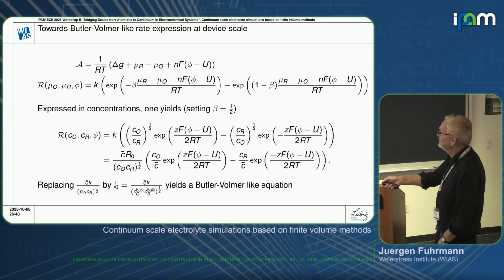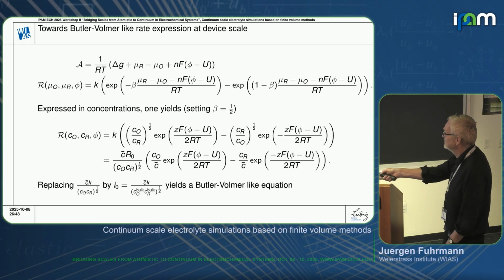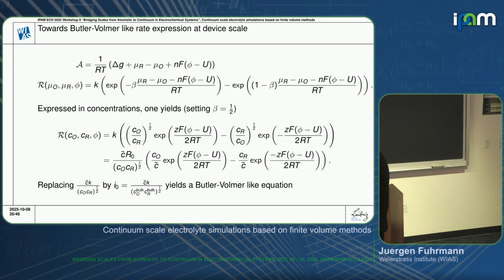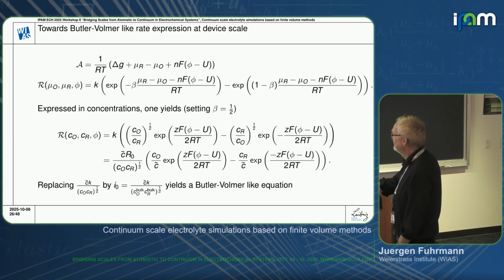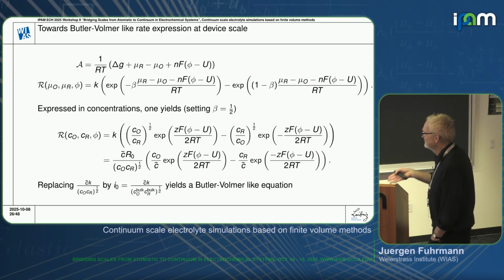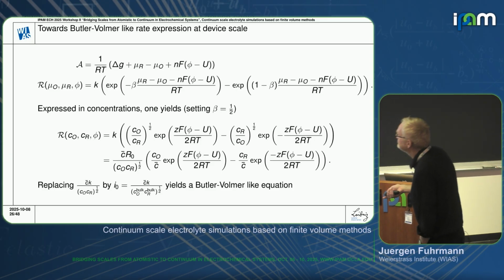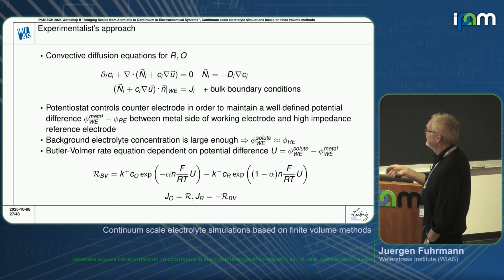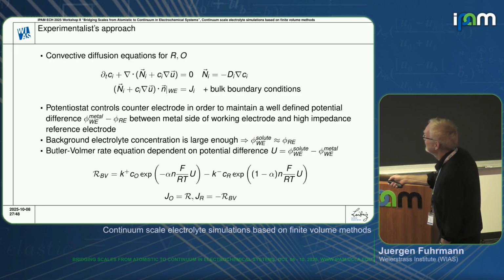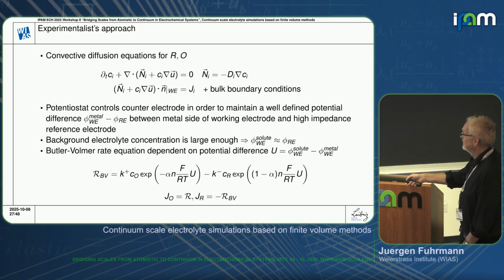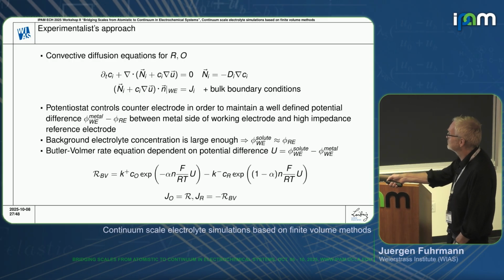So we can take our ansatz with our affinity for the redox reaction, but with this term which takes into account the jump of the electrostatic potential over the double layer, reformulate everything, and then we get a term which very much looks like one version of the many Butler-Volmer-like equations. And that's what experimentalists then do. They have this convective diffusion equation, some bulk boundary conditions, and then the reactive boundary conditions, which are Robin boundary conditions with the flux terms.